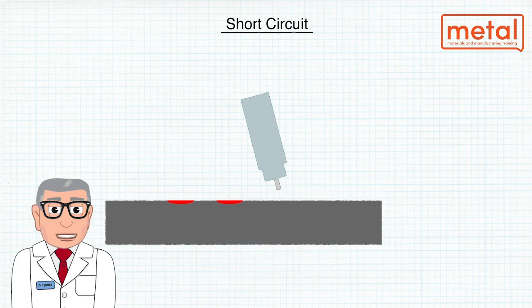The shielding gas in this case for steel is normally carbon dioxide or typically 75% argon, 25% carbon dioxide.